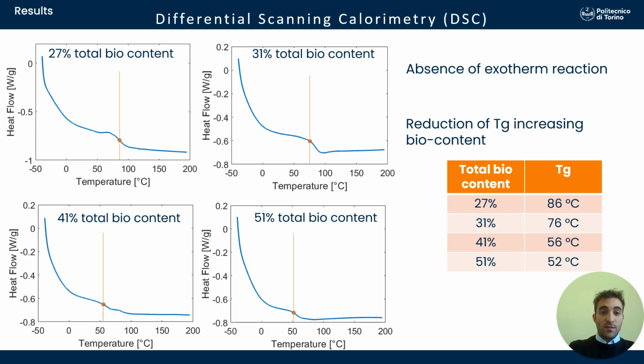In this slide, I reported the results coming from the differential scanning calorimetry test, and we can see that there is no exothermic peak because there is no cross-linking reaction, since the tests have been performed on already cured specimens. But from the result, we can see a reduction of the glass transition temperature values by increasing the total biocontent.